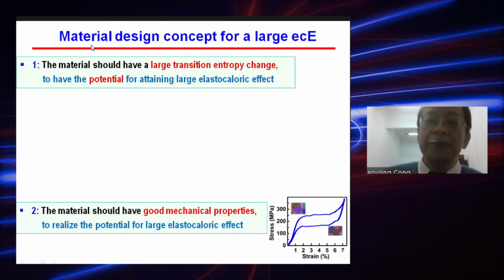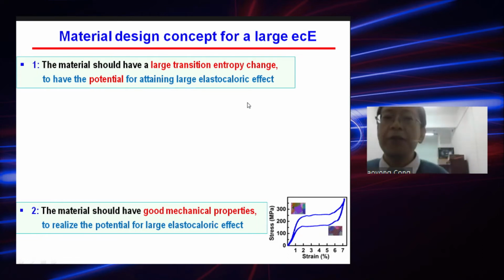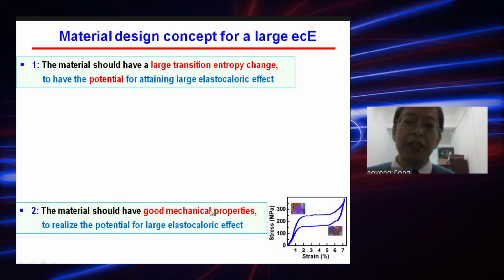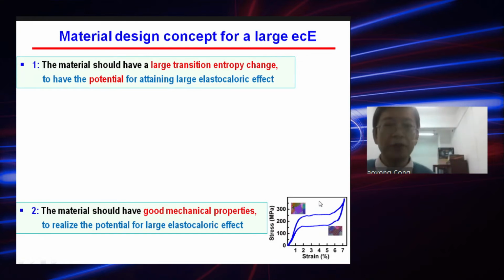Our material design concept for getting a large elastocaloric effect mainly consists of the following 2 points. First, the material should have a large transition entropy change. This will ensure that we have the potential to obtain a large elastocaloric effect. Second, the material must have good mechanical properties, so that when we have the stress-induced martensitic transformation, the sample will not break and will not deform plastically, so that the stress-induced transformation can be complete and we can make full use of the large transition entropy change.